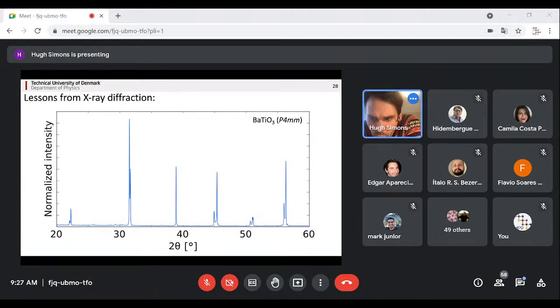This is really critical because for something with such a large technological role, we really understand very, very little about them. What we do know, however, is usually gained from the assumptions of structural symmetry. So the properties of the materials we know are very highly linked or very closely related to what their average crystal symmetry is. So, for example, barium titanate, which is one of these classical ferroelectrics, behaves the way that it does because it's tetragonal. And the way we know it's tetragonal is because if we do powder XRD, you have a pattern that looks like this, and this can be perfectly indexed as a tetragonal unit cell. And this is the way that the state of the art has been for the last 50 or even 70 years, actually.